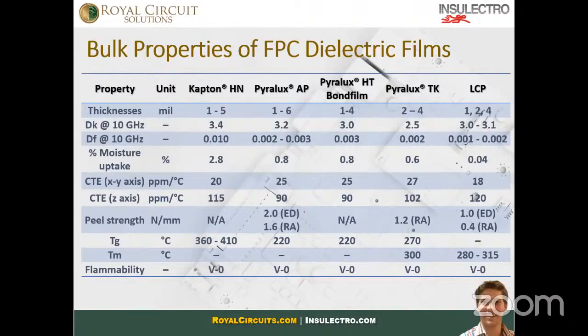We all know that epoxy systems have significantly higher CTEs and ppm, or expansion rates per degree C, somewhere in the range of 150 to 250 ppm. And polyimide materials, because they're homogeneous and because they're different in their nature, are significantly less. So as we start to heat up a board, they stop putting as much pressure on those microvias as a rigid board would. Rigid board will expand a lot. A flexible board, not so much.